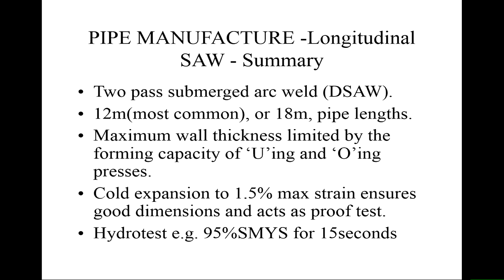Cold expansion to about 1.5% maximum strain ensures good dimensions, and that's the first proof test. Often if you badly welded the system and you miss something with the ultrasonics, when you try and expand it, the tube will burst. And then the hydro testing at 95% of the specified minimum yield stress for 15 seconds is your second pass-fail test. Okay, we don't go up to the specified minimum yield stress because there's a chance that you will cause some defects to grow in that process. And that has shown to be a reasonable level of proof test stress to actually guarantee the performance of the pipes from that process in service.